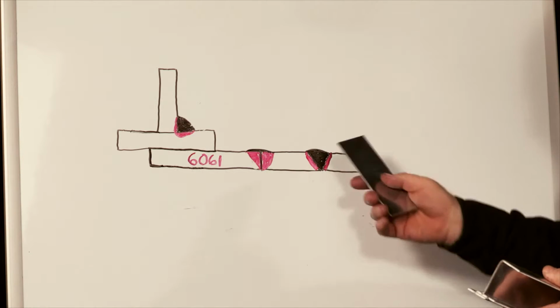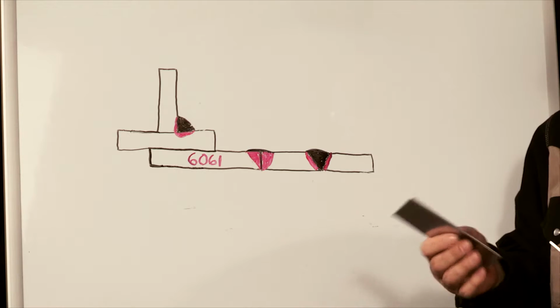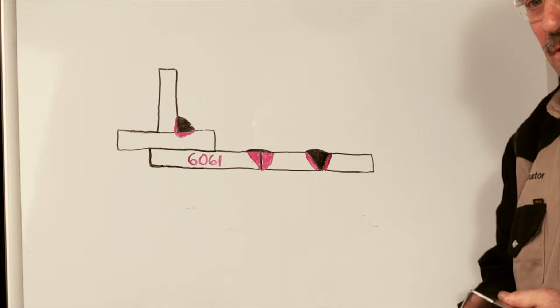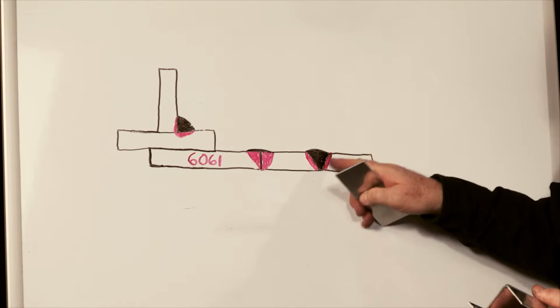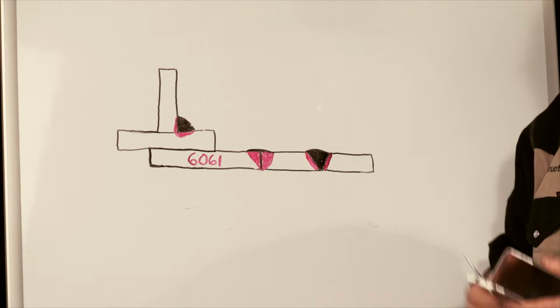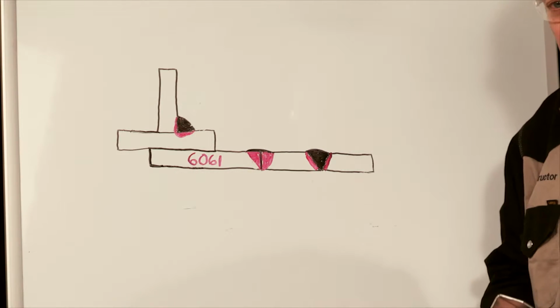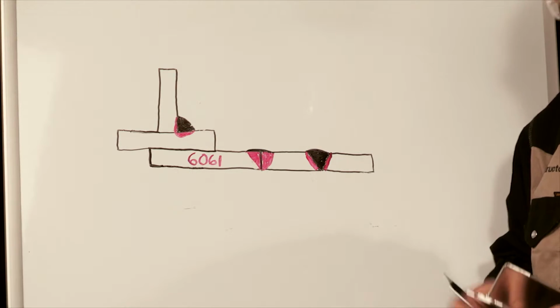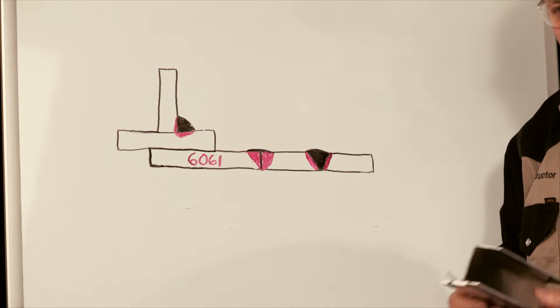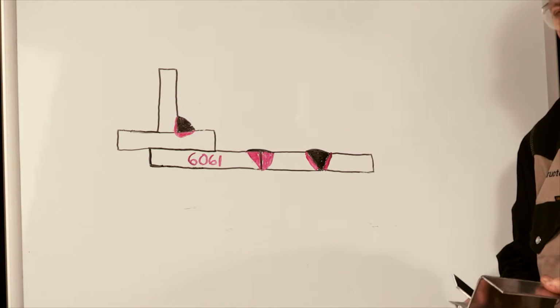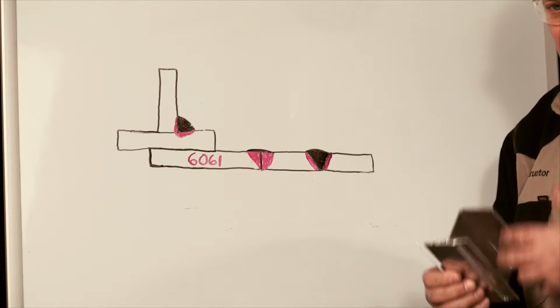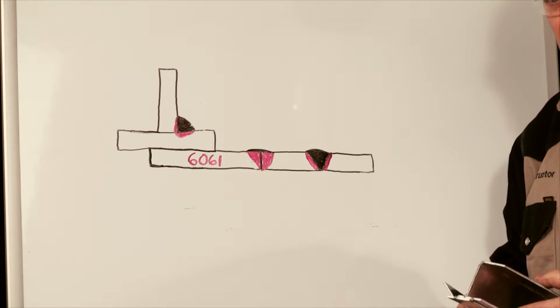And there's a good chance that's going to crack. If we bevel the pieces first, we put a 30-degree bevel on each side, or a 60-degree included angle, we can get plenty of filler metal in there and change the chemistry of that weld nugget or that weld deposit so it's not crack sensitive. We also have to be careful at the end of the welds to fill the craters, because concave hollow craters will also tend to crack. So we have to add plenty of filler metal at the end to fill that crater up.